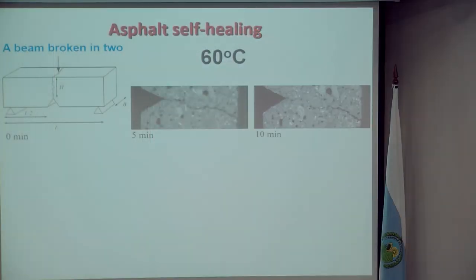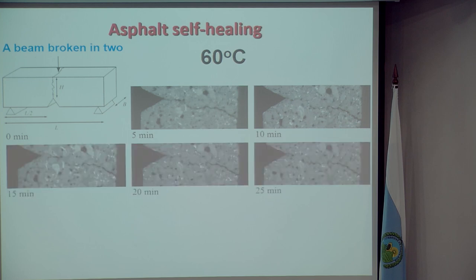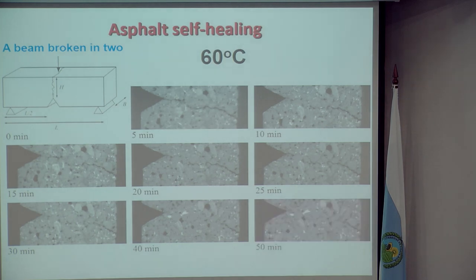So after 5 minutes, not much. 10 minutes, we're starting to see something. 15, 20, 25, we're now seeing quite a lot of that crack or fracture has actually disappeared. 30 minutes, 40 minutes, 50 minutes. And by the time we got to 50 minutes, we could take that specimen back out of its mold or chamber, place it back onto that three-point bending test, and repeat the test and get another value. So we know that bitumen and asphalt already has that capability.